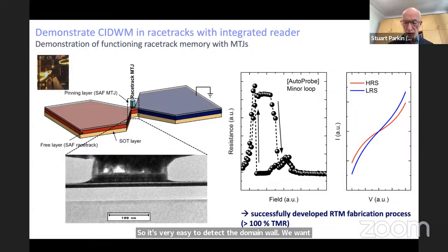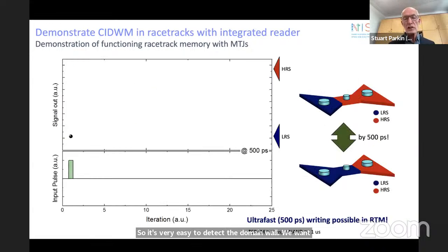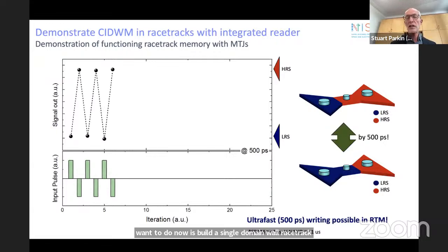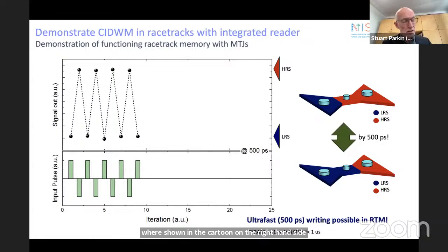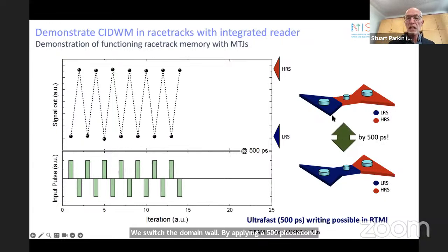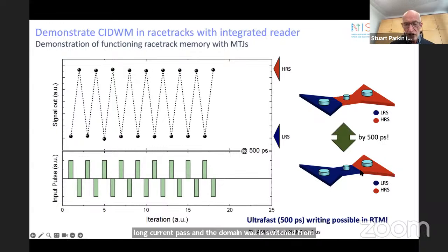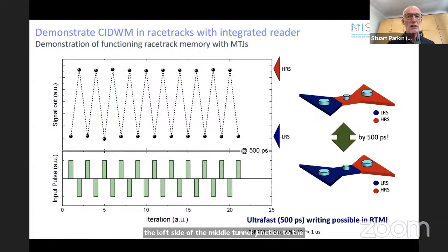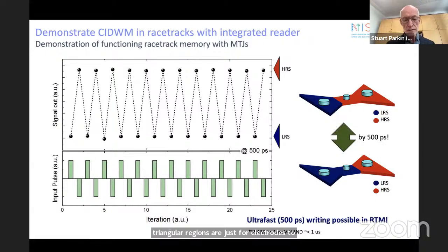What we want to do now is build a single domain wall racetrack, where shown in the cartoon on the right-hand side, we switch the domain wall by applying a 500 picosecond long current pulse, and the domain wall is switched from the left side of the middle tunnel junction to the right side. Basically, the rest of the structure, these large triangular regions, are just electrodes to detect the domain wall through the tunnel junction resistance.